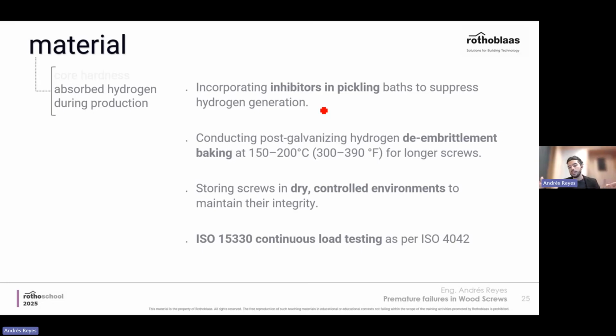So no hydrogen is generated in the bath. And then as well, for some sizes or in general, the de-embrittlement baking, a baking process at the end of the production, can also facilitate the escape of the hydrogen inside of the fasteners. We do it for some sizes of screw as well. It's part of our standard production. Then storing screws in a dry controlled environment, and finally performing ISO 15330 continuous load testing.